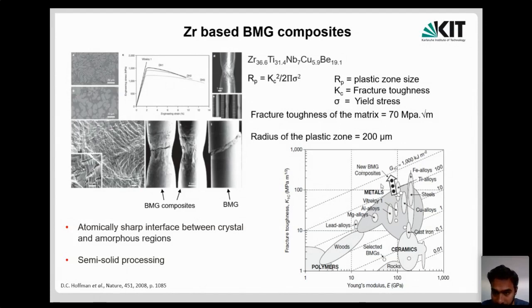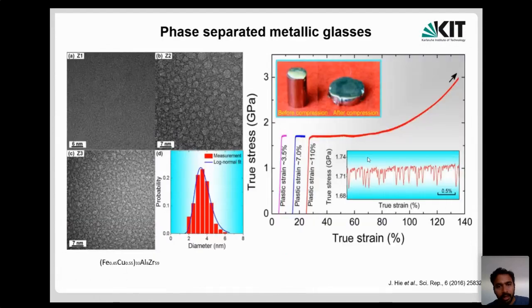Okay, and if you see the fracture toughness of these glasses, they are very, very high, almost in these black dots here. That shows the new bulk metallic glass composite. So you have crystalline dispersion in an amorphous matrix here. Then you have a phase separated glass, which I talked about, where you have amorphous phase dispersed in an amorphous phase. Before compression, you see the glass, and after compression, you see that it almost became a flat surface. You can also see that in the stress strain curve. So this is an amorphous dispersion in an amorphous matrix. This is the logic: the shear bands are not propagating because you have a second phase, the other amorphous phase, which is obstructing it.